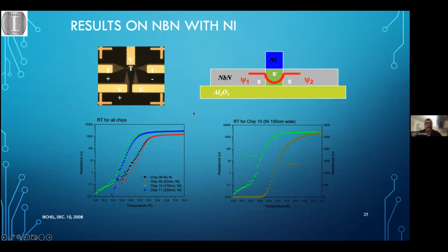Okay, and then I got similar results. I'm not going to go into the details here, but because of this system, the niobium nitride was so thin and so resistive that many times when I put the nickel on top, I could get absolutely complete destruction of the superconductivity. That required a more extensive study. The capabilities were there, but there was no funding, and the funds ran out, at least for my side. That's where everything stopped, but I got to the point where I repeated the ideas.